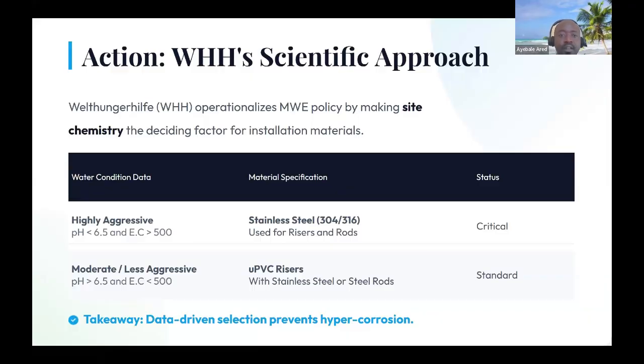As WHH, we operationalize the Ministry of Water and Environment policies by making the site chemistry, or the water quality testing for ambient conditions at the site, the deciding factor for installation materials. Drilling supervisors at the site during pump testing move with pH and EC meters, and as they pump test, we measure electrical conductivity and pH. We do this because we don't want compromises from transportation, as a few chemicals may change the quality. We want the real ambient conditions of the aquifers, so we prioritize having mobile test kits at the site.